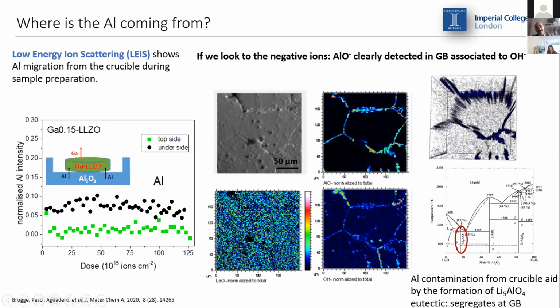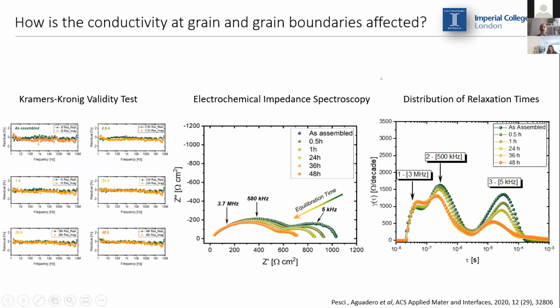The fact that the grain boundaries have got a different composition from the bulk is something that was puzzling us. So we decided to carry out electrochemical impedance spectroscopy, and to do that, we don't just use impedance spectroscopy, but we combine impedance spectroscopy with the Kramers-Kronig validation test, which is a test that we do in order to see the quality of our data and to see how good the fitting could actually be. And we also combine EIS with distribution of relaxation times.